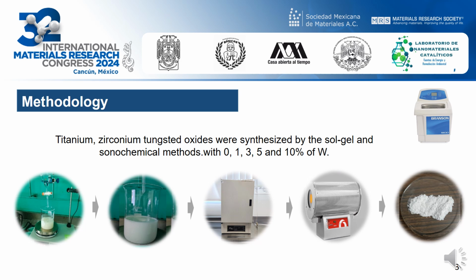Then, both solutions were mixed maintaining an alcohol-water molar ratio of 1:16. A system at room temperature with constant stirring of 800 revolutions per minute was established, and then the dripping of the water solution at pH 3 was adjusted for automatic dosing during 2 hours. Subsequently, stirring continued for 24 hours to achieve aging, and the first drying was carried out until the water and alcohol were eliminated, in an oven at 80 degrees for 48 hours.